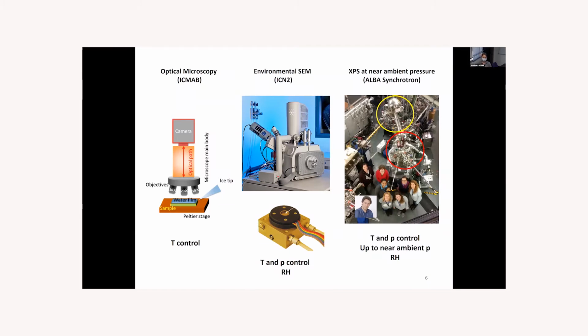Well, our setup in the ICMAB is the optical microscopy coupled with the high-speed camera that will visualize the fast occurring freezing of water, and the Peltier stage, which allows us to control the temperature of the surface or the particle. We also use the environmental SEM at the ICN2, which has a specialized design stage, which allows us to control the temperature and pressure in the chamber in order to have the suitable relative humidities.